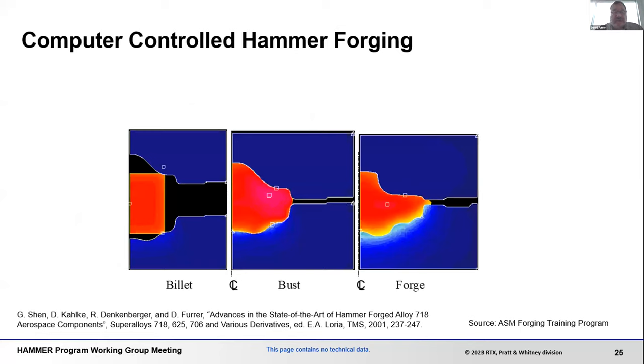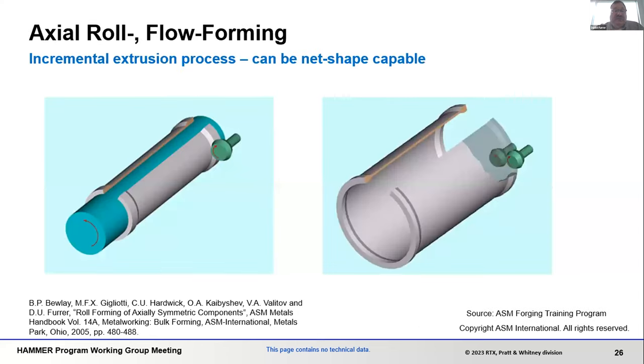So looking at modeling activities, again, an old paper from a TMS conference, where you can forge parts in a hammer and control very, very closely the temperature, strain, and microstructure within the part. Again, this is not incrementally making a part, such as incrementally making a shaft per se, but it's incremental deformation to get a final part. This is an example of true incremental deformation. So if you want to do extrusion and you want to extrude a hollow tube, you can do that.